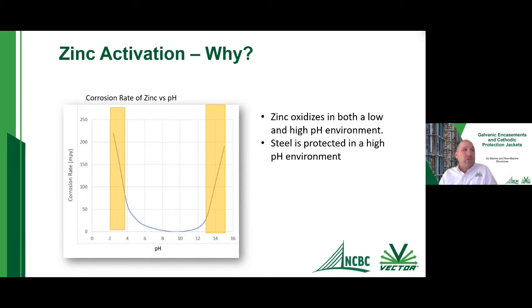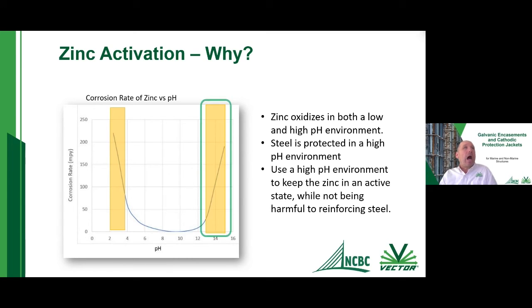If you have a low pH environment, steel corrodes in a low pH environment. Steel is actually protected in a high pH environment. So you're going to want to use a high pH to activate the zinc, because our corrosion rate of zinc is much higher in a higher pH. Plus, then it's not damaging or detrimental to our reinforcing steel as well.